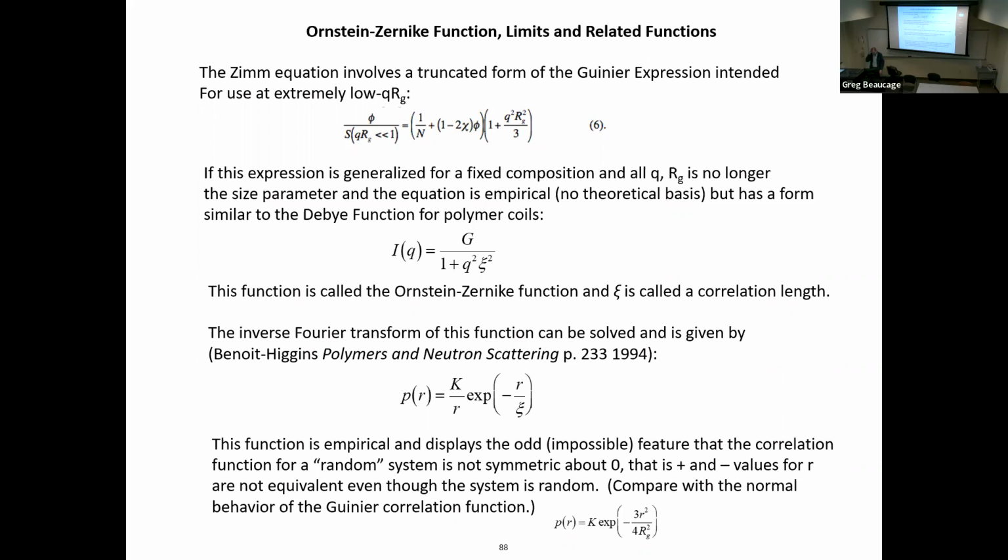And it comes from the idea, like when you shoot a beam of X-rays through a liquid, you get a hump. So like the atoms are kind of located at some distance, a correlation distance. You could say it's the middle of that hump, the amorphous halo, right? So there's not a diffraction peak that has a real position, where you can do Bragg's law to figure out what it is. It's just a hump, and it's not even really a Gaussian hump. It's kind of a log normal hump. It's got a tail to it.